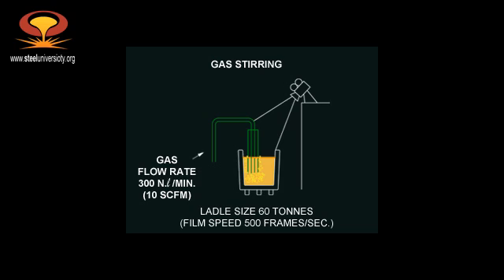That gives rise to re-oxidation. This next sequence shows ladle stirring where gas is being injected into the ladle through a lance. The flow rate of gas entering the ladle is 300 litres a minute. The ladle is a 60-ton ladle and the film is recorded at 500 frames a second. We can see that the bubbles generated — and behind the stopper rod we see a very large bubble being generated. This bubble is certainly not small.